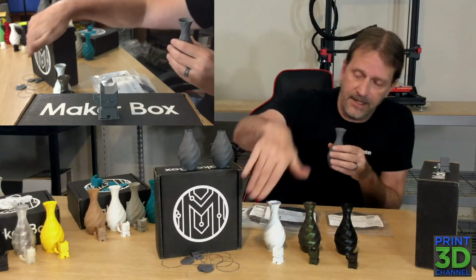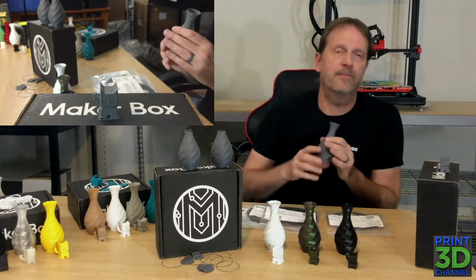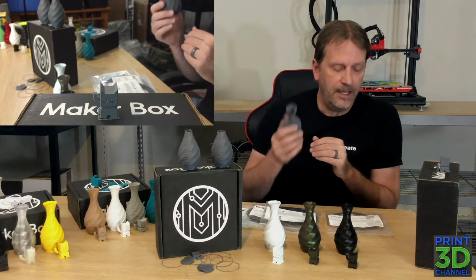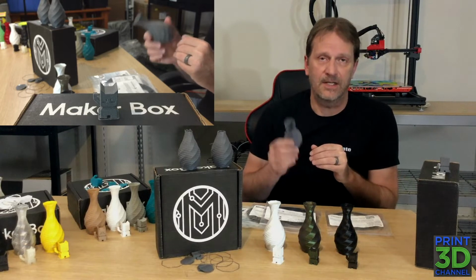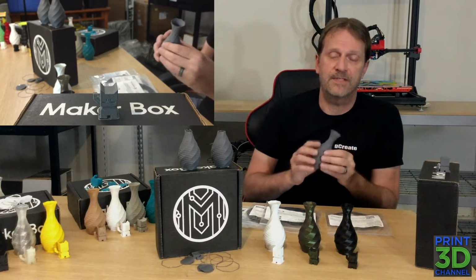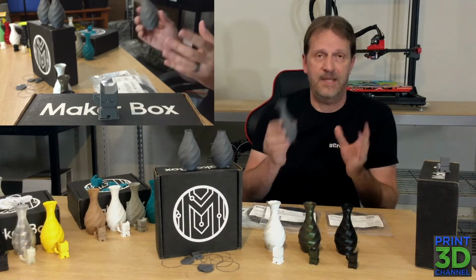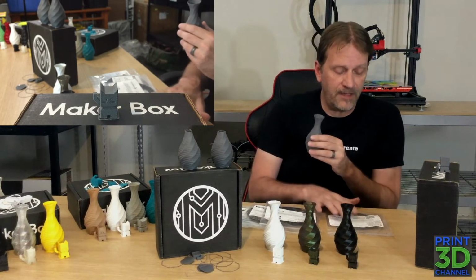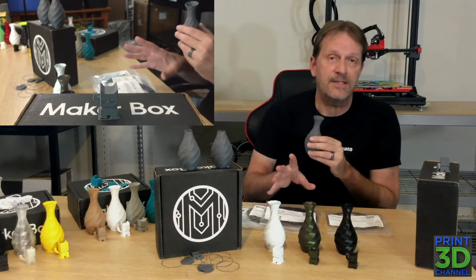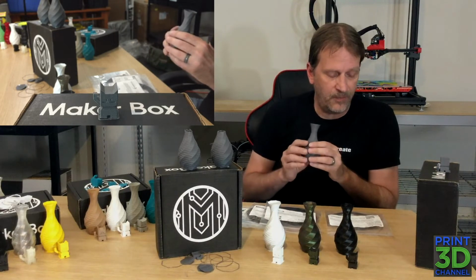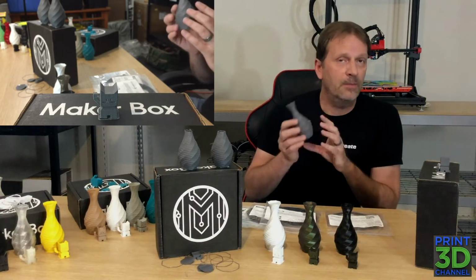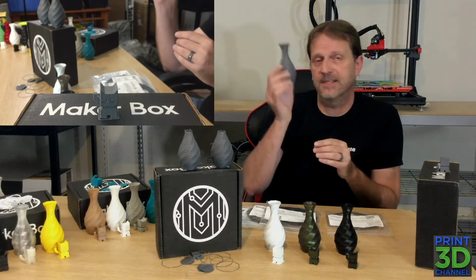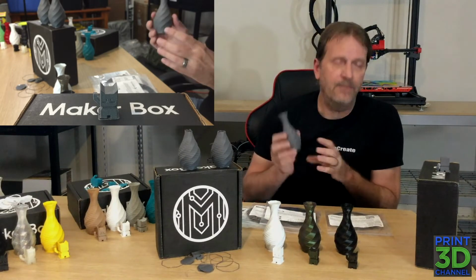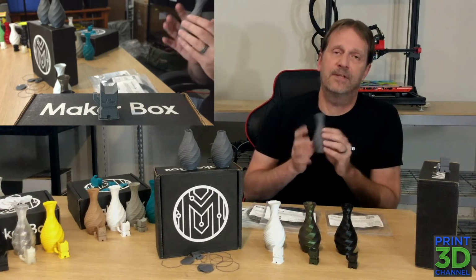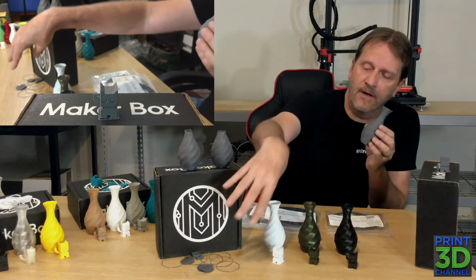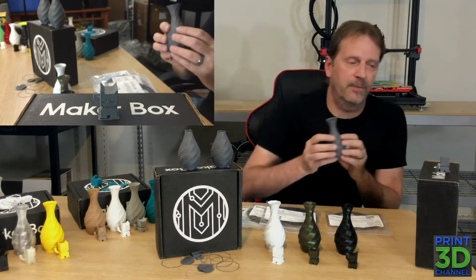Now, like I said, I did have some issues getting started. I did dial up my hot end to 250 and my bed temperature to 70C just to get us going, but it did give me some print success once I got to a certain aspect of that temperature range, which was 250 on the hot end and a bed temperature of 80C, which is above the recommended temperature. I did print these out at 30 millimeters per second just to make sure I got my nice layer bonding going on. And I had my cooling set to only 20% for the entire prints. And after all those failures, I managed to get out a couple of prints that I'm happy with.